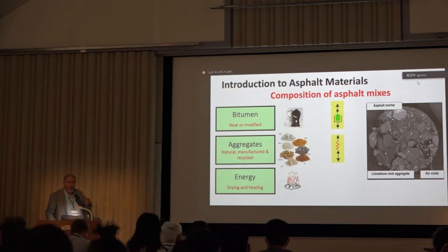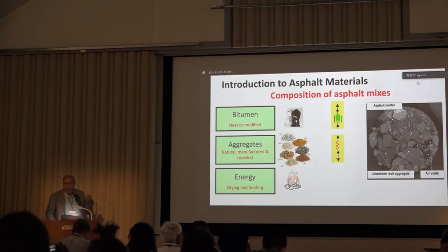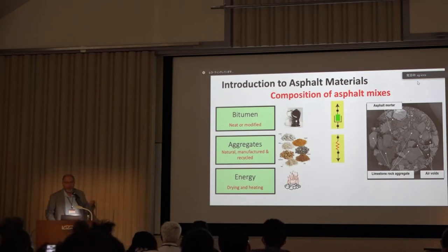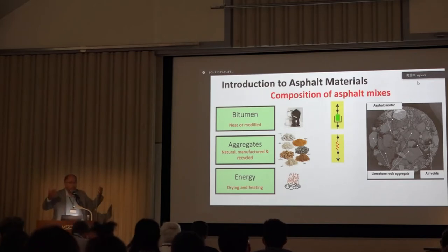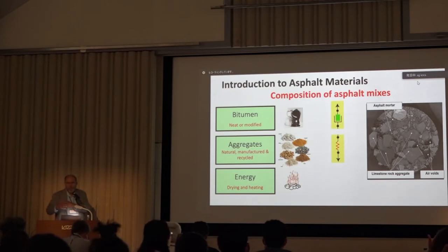And when we talk about healing, what will heal there if we have a crack? Do you think that the aggregates will heal if they crack? I don't think so. It's the asphalt. So we focus on the healing of that binder, actually. And because it's a viscous material, unlike in the Portland cement concrete, where we talk about viscosity only at the fresh state, the viscous behavior in the asphalt continues, and depending on the ambient temperature, the temperature of the asphalt, this viscous behavior can be predominant, and when the asphalt melts, we think that it would self-heal.